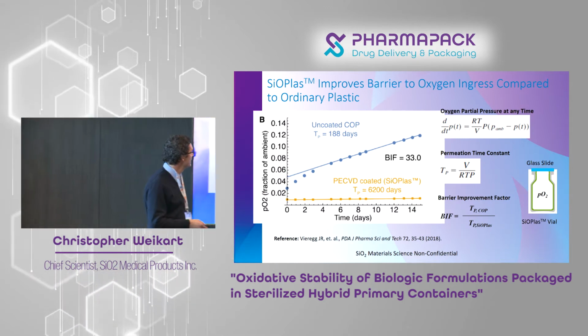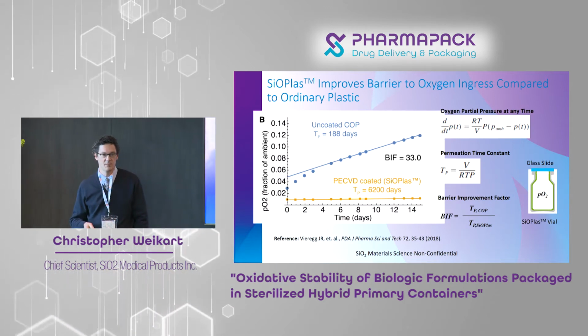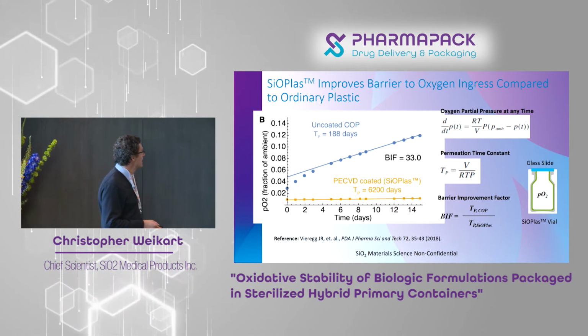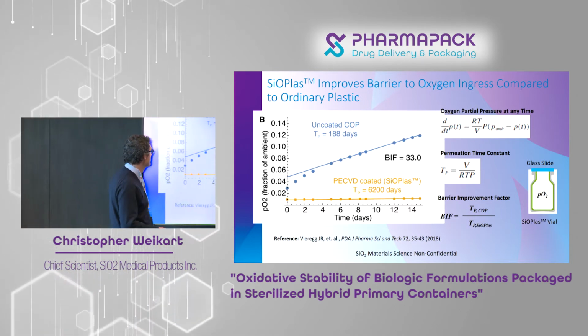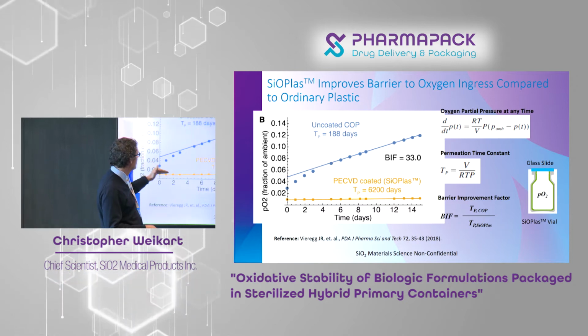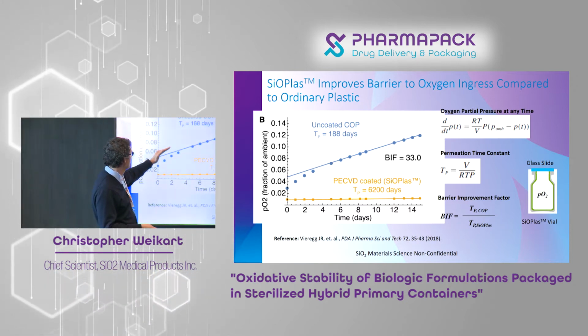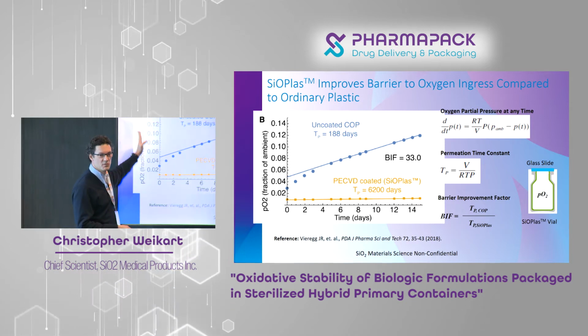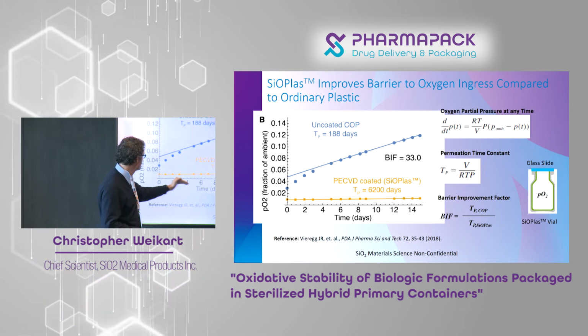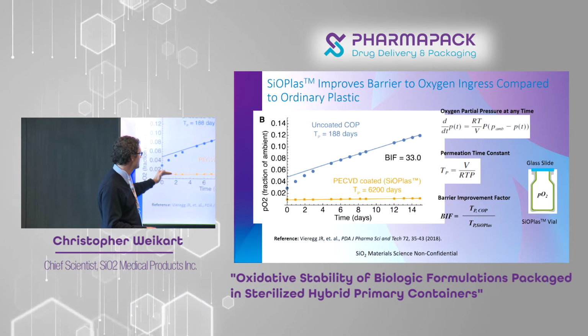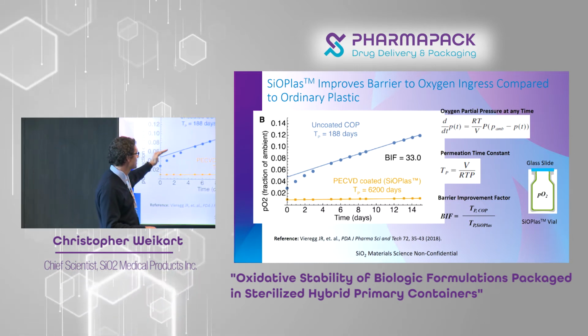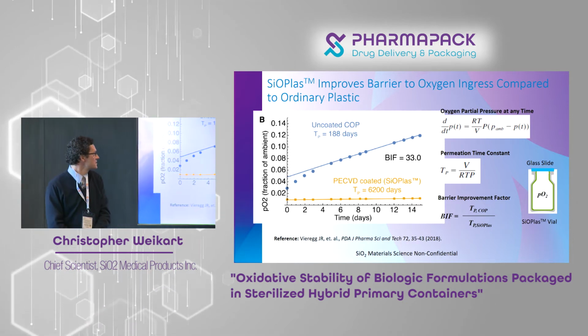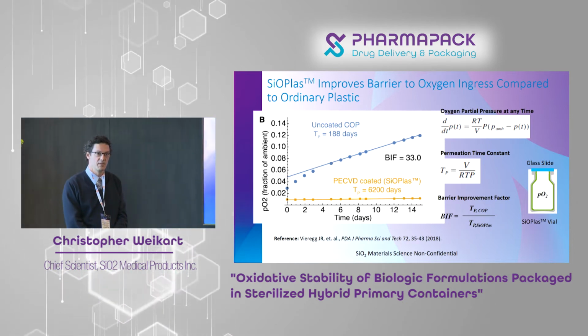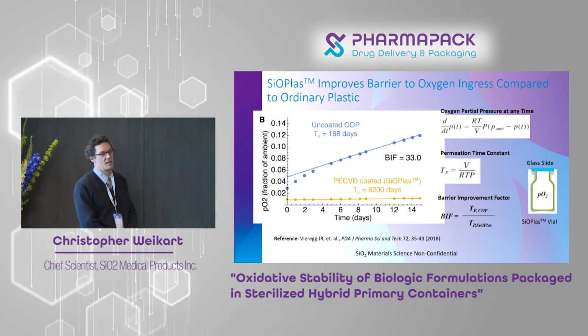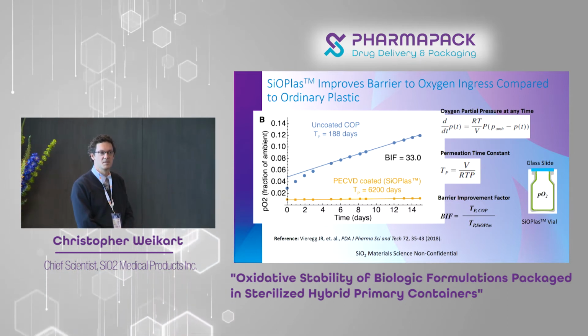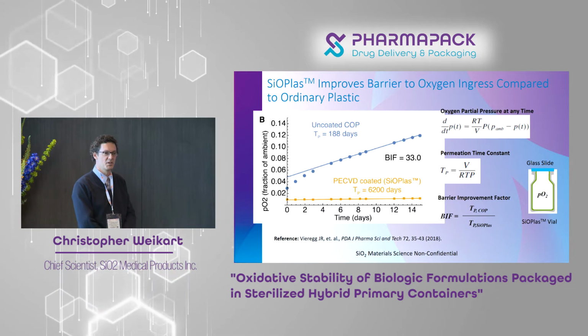We measured the oxygen ingress through a method we developed internally. And basically, this just shows you a little bit of the math and the difference between a coated container and an uncoated container. You're basically measuring the partial pressure of oxygen in the container over time. You can see how very little ingress occurs in the PCVD coated container versus an uncoated. We effectively increased the barrier, reduced the permeability by about 33 times in this case. In some other cases, it's 60 to 100 times, depending on the container geometry and what we want to achieve.